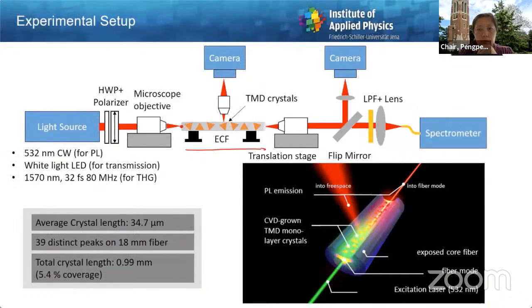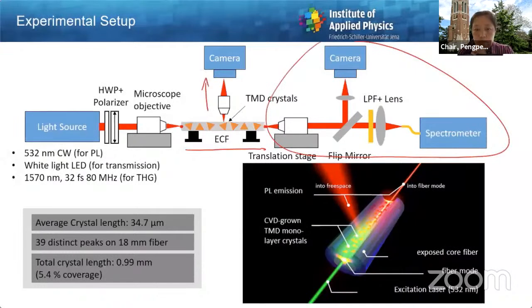Down the optical fibers, and then we observe what is coming out of the other side using cameras and spectrometers, or we observe the light which is emitted sideways using the camera. So we use sideways emission basically for determining the area coverage of our MoS2 on the optical fibers. You can basically just count the number of photoluminescence peaks. And for this specific fiber, I'm going to show you the results here today.